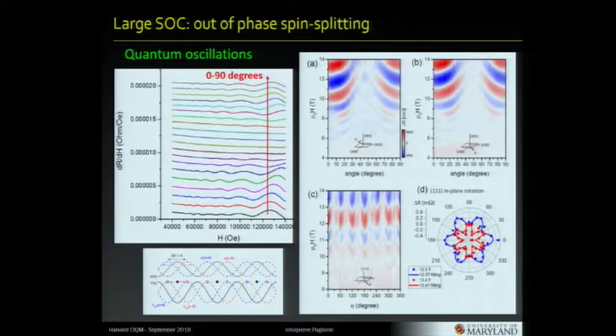First of all, this probably was explained to us by, not Schoenberg, but Pippard, one of Pippard's old books, who explained that if you're in a limit of strong spin orbit coupling, in real space, these are atoms here, the black guys, in real space you'll have some splitting of the potential due to the ions in the lattice. And that will, in a certain configuration, give you a phase shift of the oscillation. So you'll have two spin split oscillations that will be out of phase by pi in this limit of strong spin orbit. And so this is what we think is happening here.